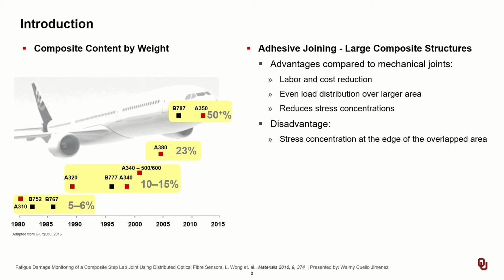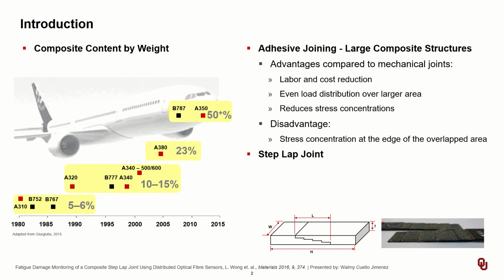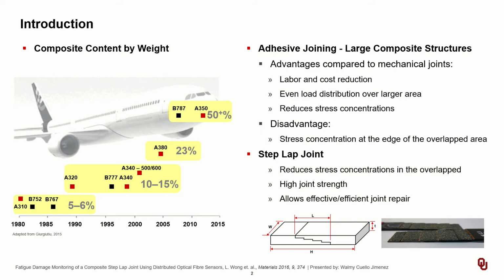In order to minimize the peak stress, or the stress concentration, many groups have proposed the use of step-lap joints as an efficient joining methodology. A step-lap joint consists of manufacturing the parts with a series of steps that result in greater bonding surface area, reduction in stress concentration at the end of the overlap, high joint strength, and more importantly allows for efficient and effective joint repairs. Ultimately, reaching more than 50% composite content by weight in the aerospace industry could not have been achieved without the use of step-lap joints.